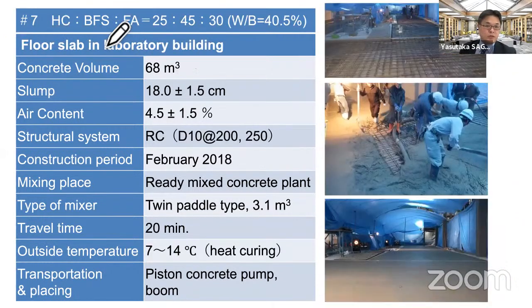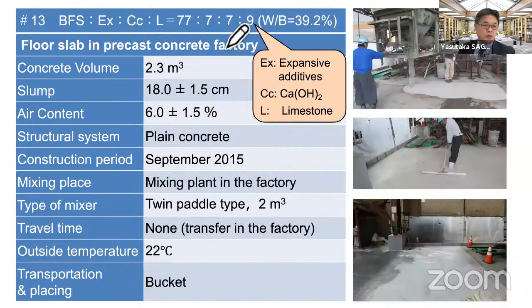And the next application is a ternary blended binder, HC, blast furnace slag and fly ash of 25%, 45%, and 30%. It is ternary blended. The last example is a very challenging case compared to ordinary cement concrete because it is a concrete without Portland cement. No Portland cement is used. 77% blast furnace slag, 7% of expansive additives, 7% of calcium hydroxide, and 9% of limestone powder. Calcium hydroxide performs as an activator of blast furnace slag.